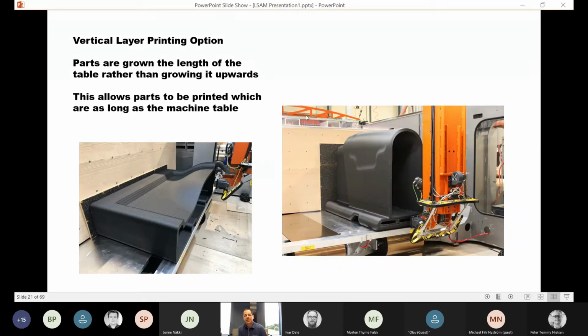The next option is what I mentioned earlier, the vertical layer printing option. With this, the nozzle is rotated 90 degrees and a movable wall is mounted onto the fixed table. Parts are grown the length of the table rather than growing the part upwards. And this allows you to print a continuous part, which is as long as the machine table itself.